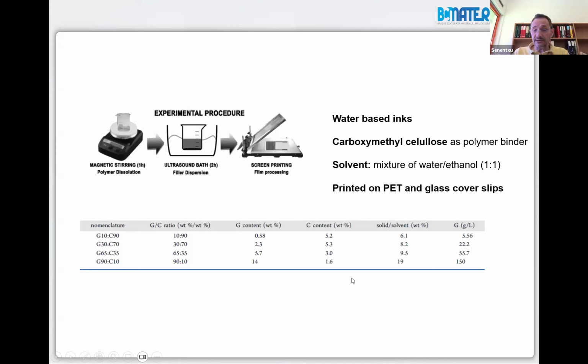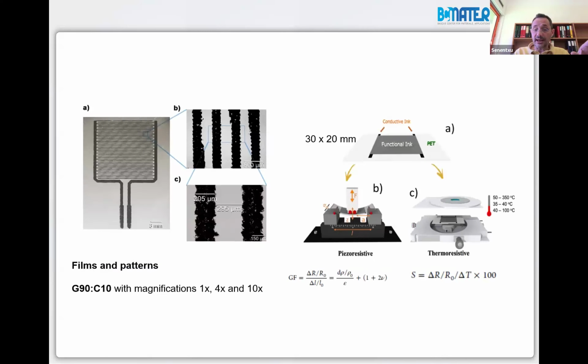Obviously, by changing the graphene content, there is also a variation in the viscosity, that means the printability, probably not very suitable at the higher graphene content for inkjet printing. But for screen printing, that we are using here, we can maintain the printability by the proper mixture of water and ethanol, but you have a huge variation in the functional properties. And you can have from a dielectric to a high conductor to a thermoresistive to a piezoresistive. So you can have a complete system just by some carboxymethyl cellulose, water and ethanol, and graphene. Basically, carbon and water everywhere.